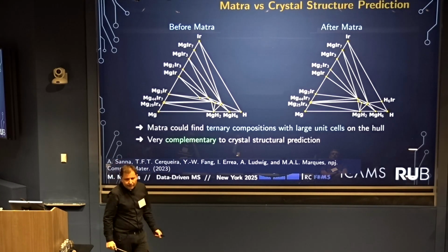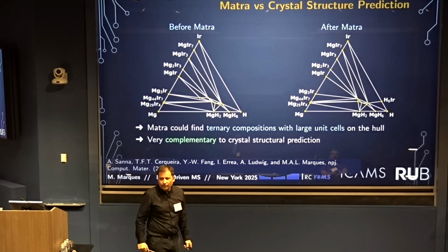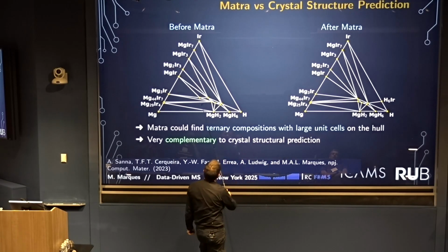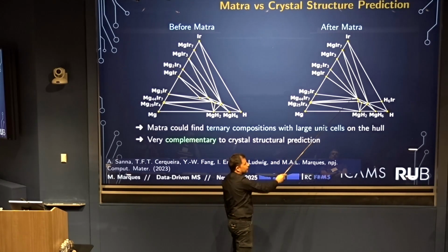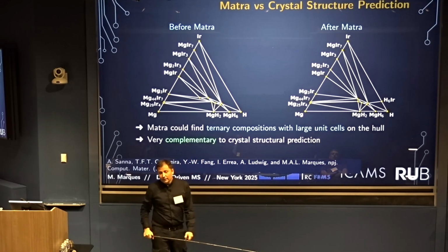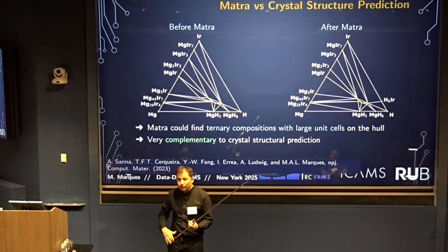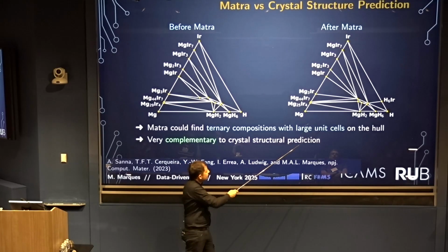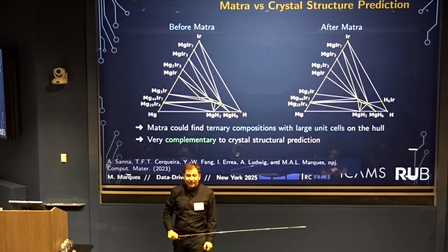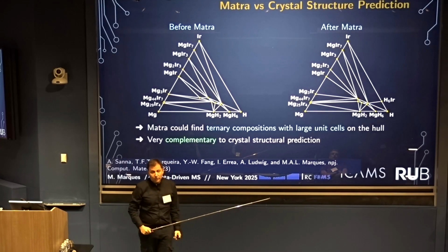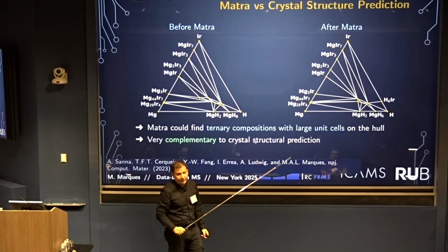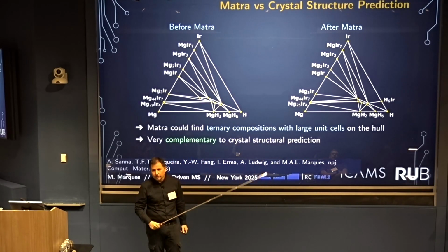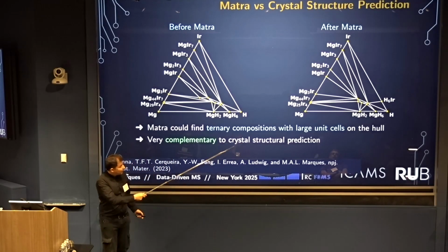And the other day, I actually wanted to plot the phase diagram, and I got this. And it's different, right? See, here there's 1 point, and here there are these 2. So there is something that showed up here that was not in the structural prediction. This actually came automatically through our generation without looking specifically at this chemical system. It just came out. And this is something that has 40 atoms in the unit cell. So you will never get it in structural prediction. So I'm not saying this is a replacement for structural prediction, but you can access regions of material space that you cannot with structural prediction, especially things with a lot of atoms. So we were kind of happy.